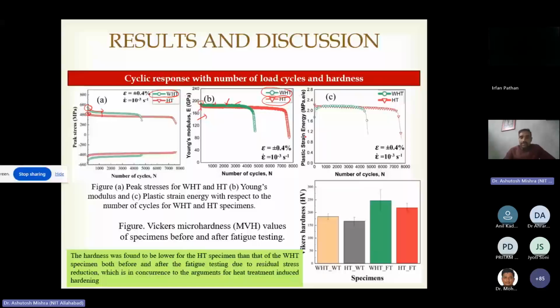Then plastic strain energy with number of cycles is shown here for heat treated and without heat treated samples. And we noticed that plastic strain energy is reducing after a large number of load cycles. It means it is losing its load bearing capability slowly. However, the without heat treated sample is losing its load bearing capacity, that is cyclic load bearing capacity, at a faster rate. So this plot of plastic strain energy variation with number of cycles particularly gives us this information.